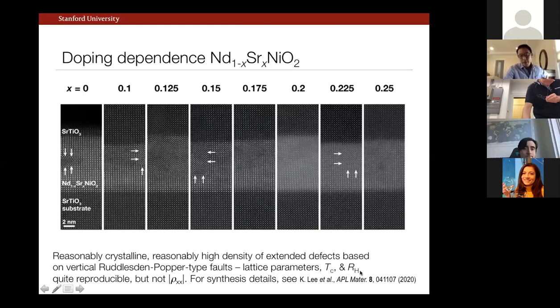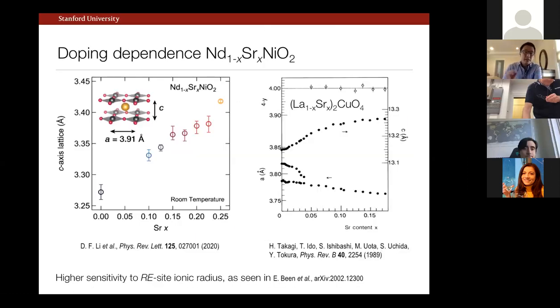these are quite quantitatively reproducible. But as far as the magnitude of the resistivity, there's a fair amount of jitter sample to sample. And we believe that's coming from the details of the density and distribution of these sorts of extended defects, but we'll go into that in a moment. So first, in terms of the doping dependence, let's first look at the crystal structure.